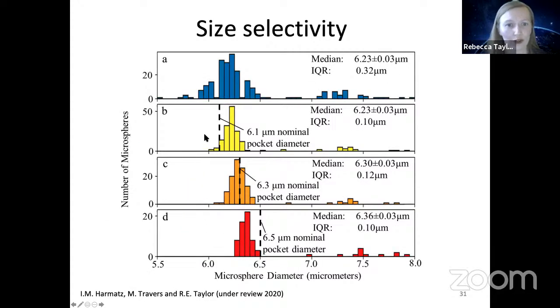Furthermore, what we also showed was here at the top, we've got this wide distribution of bead sizes, but we can actually tune the size of our pockets and select out different subpopulations from this one, right? So you have a polydispersed input, but you've got a much more tightly grouped output, right? And you can see particularly the interquartile range went down threefold for the outputs. So here we have some really powerful size selectivity.